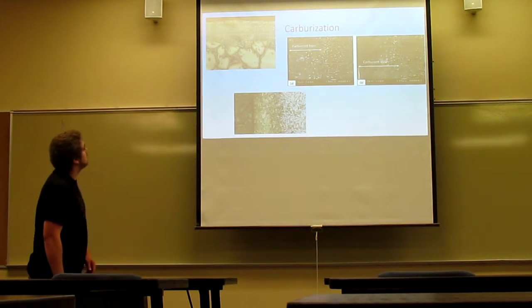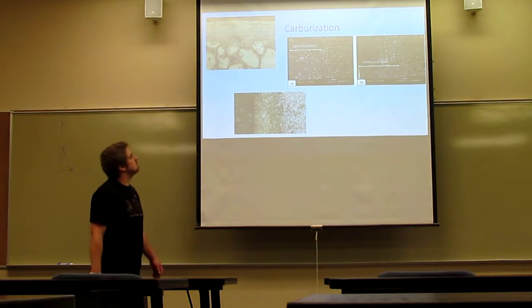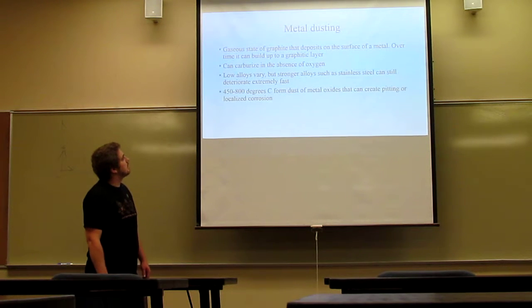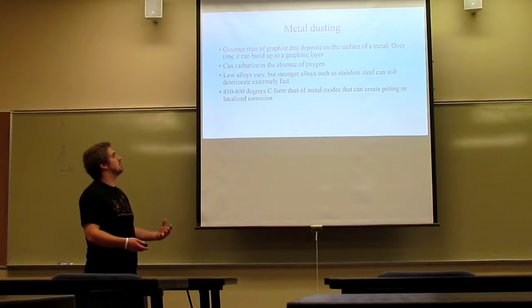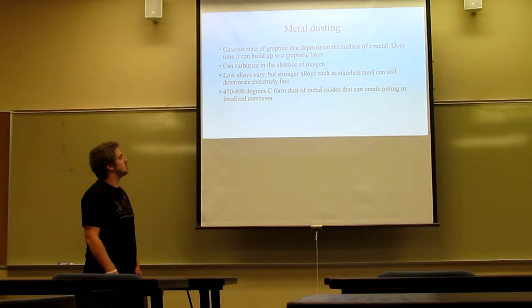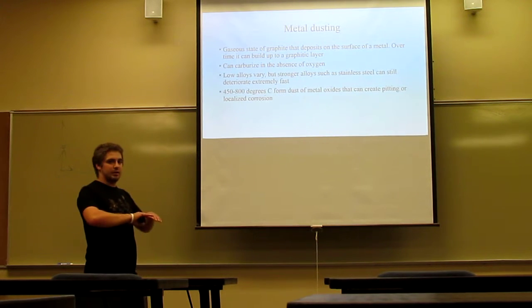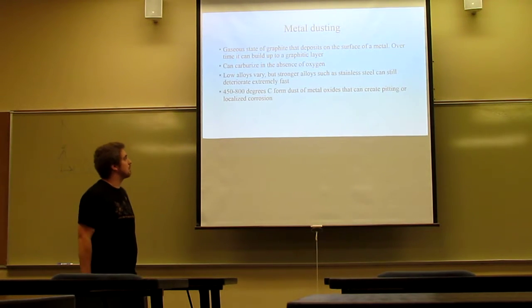And I have a few photos here of carburization. So we have metal dusting. The gaseous state of graphite deposits on the surface of the metal, and that creates a graphitic layer. It can carburize in the absence of oxygen.